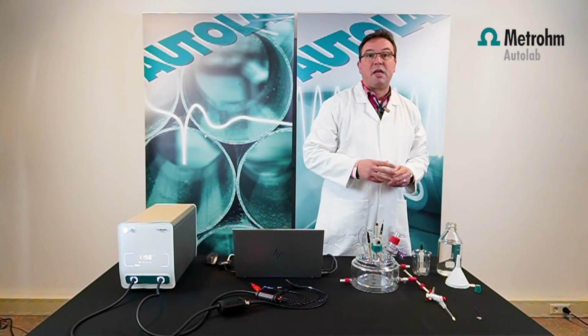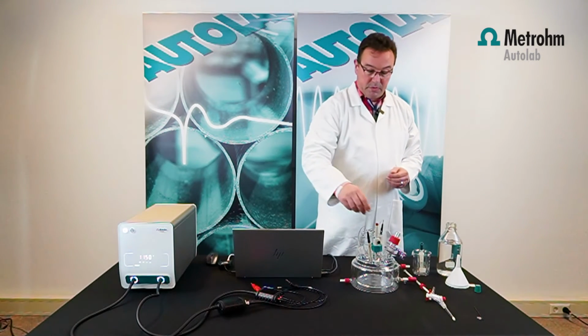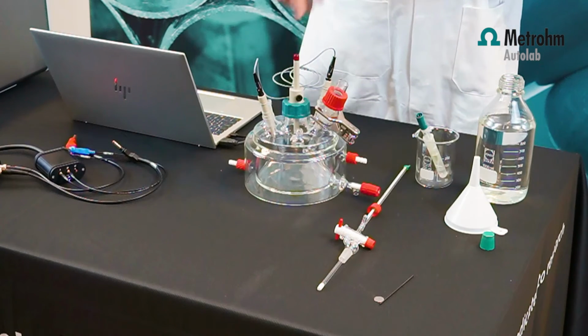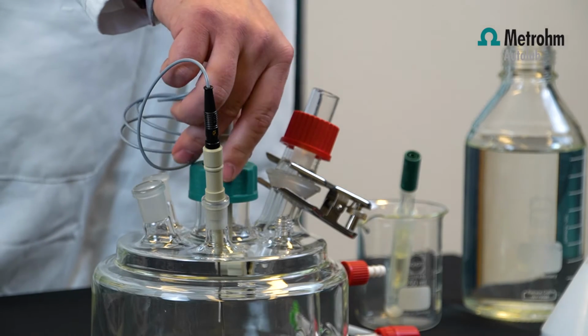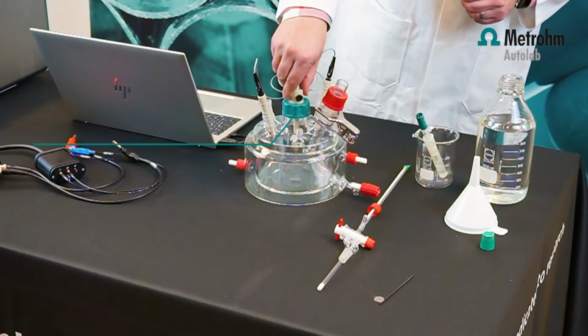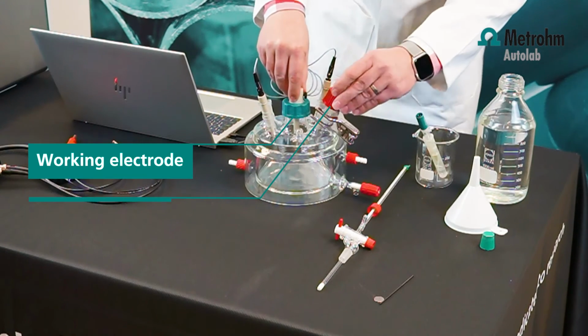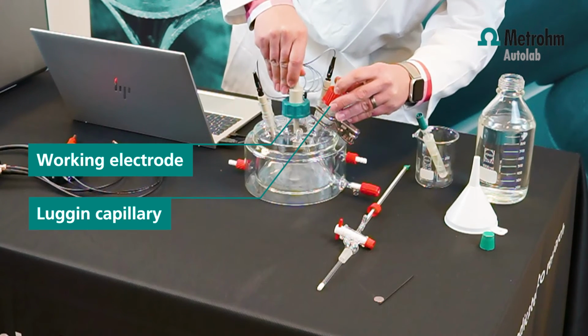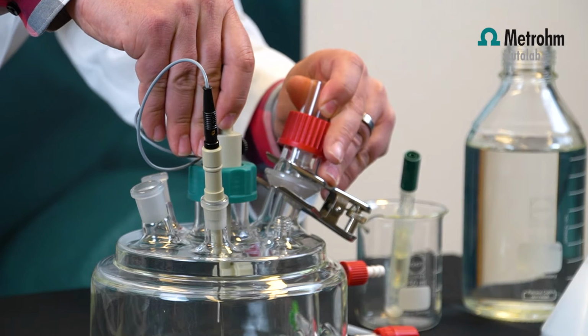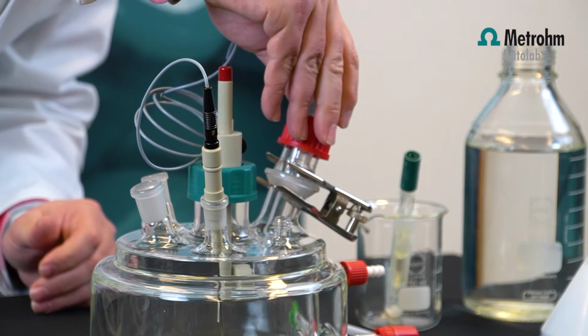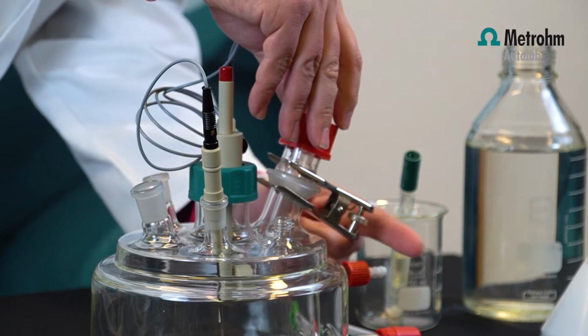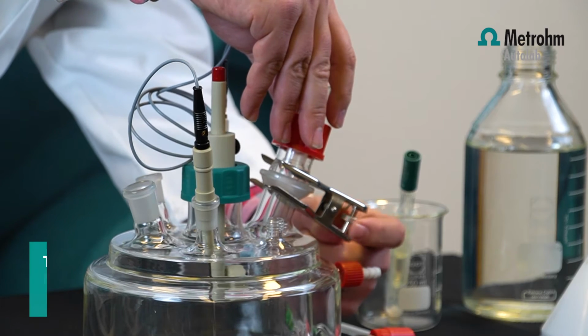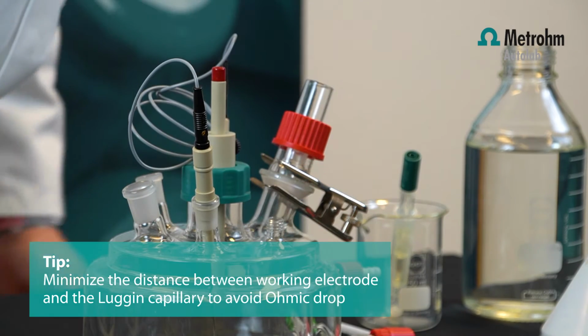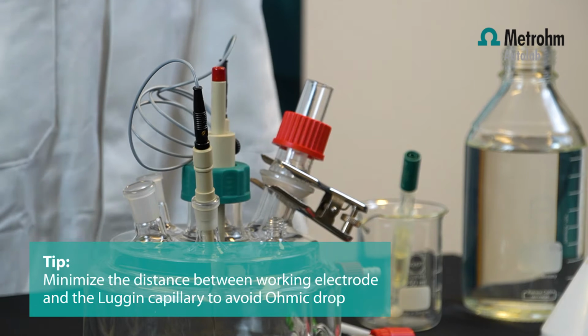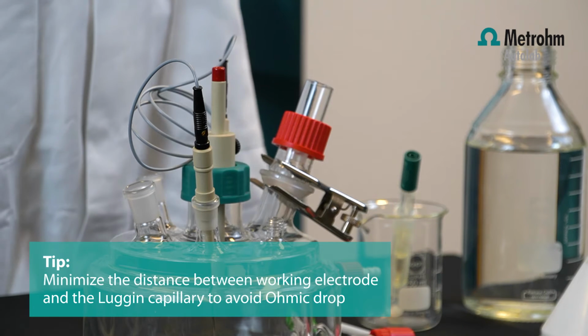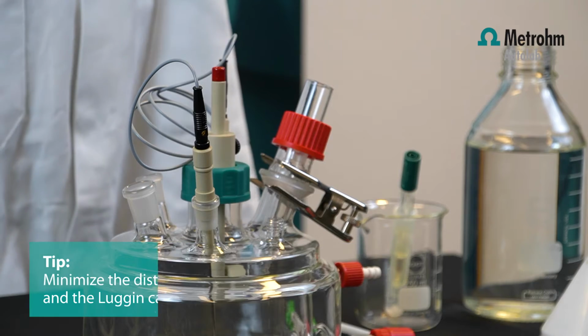It's used for flat samples, metal samples, and you can mount it with a rubber ring, as I showed you before. The sample holder is placed into the corrosion cell, and the distance between the working electrode and your Luggin capillary can be adjusted by raising or lowering the sample holder and the position of the Luggin capillary. You can fix the capillary with this clamp, and now the reference electrode is as close as possible to the working electrode. So you have a very low ohmic drop in between the reference electrode and the working electrode.